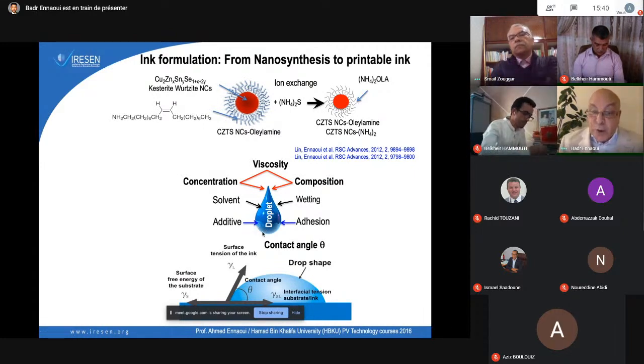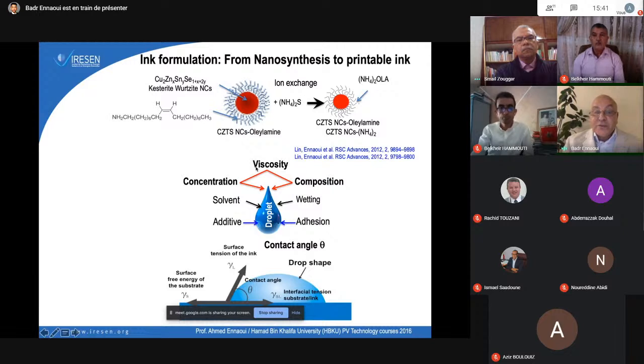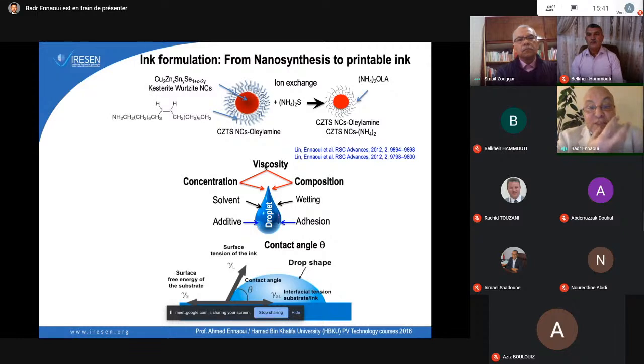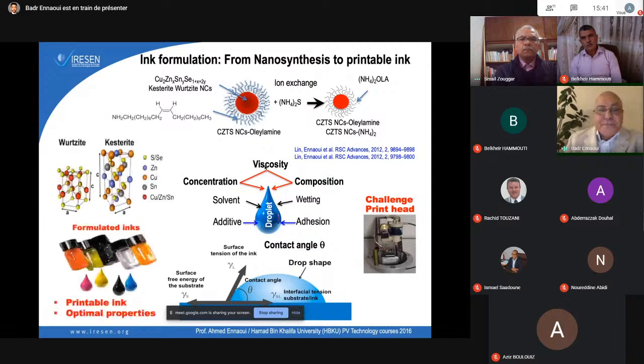if you take a drop of your ink, you have a solvent, you have additive, you have the adhesion, the wetting, the concentration, the composition, and the viscosity. Composition and concentration are the drivers of the viscosity. So all this information is in one droplet. And you have to study this droplet using, for example, contact angle in order to see if you can wet the whole surface with your drop, or you can make only drop by drop, one near the other, and they will join together, etc. This is a very important science, which is nanosynthesis, ink formulation, and drops in inkjet printing. So this is the challenge in this method of inkjet printing and ink formulation.